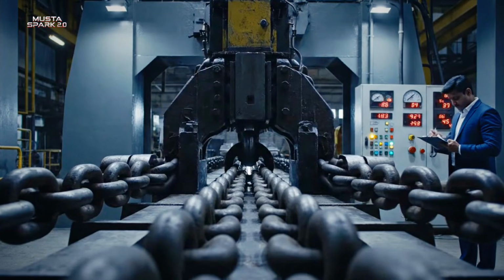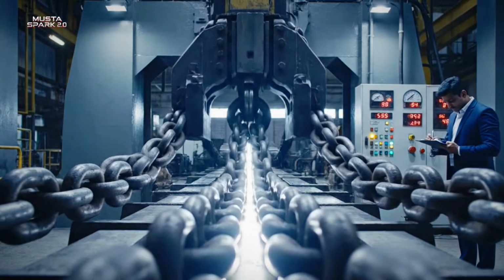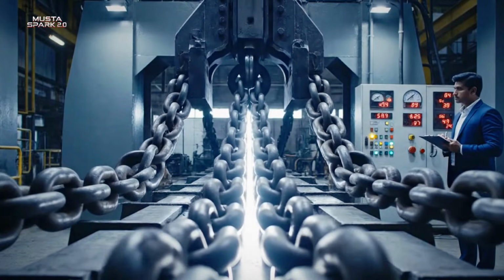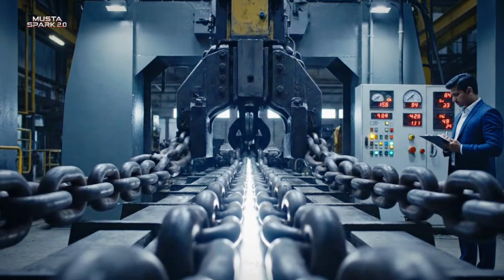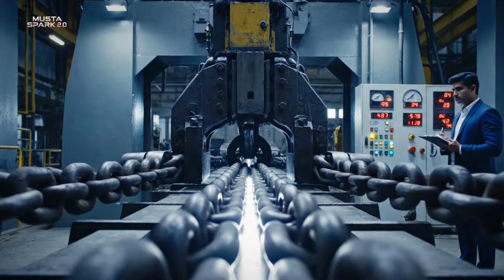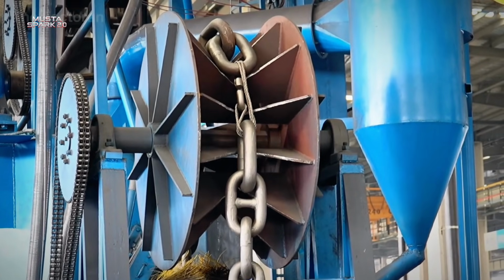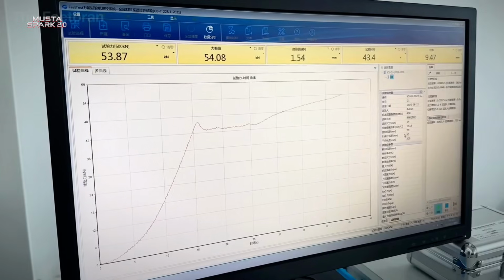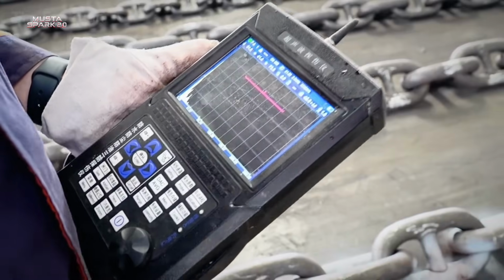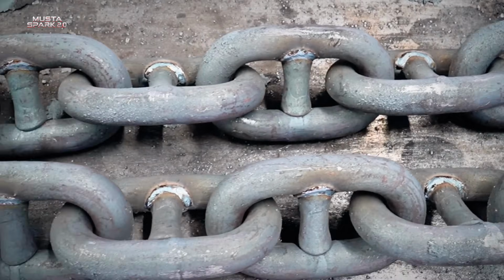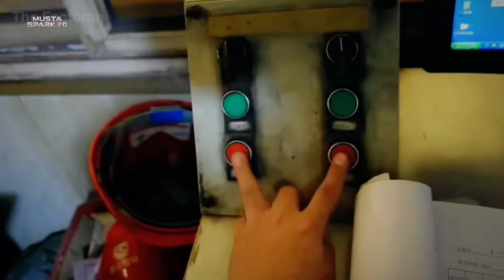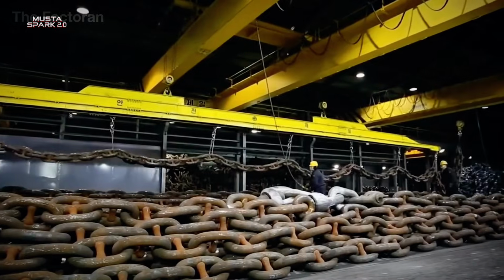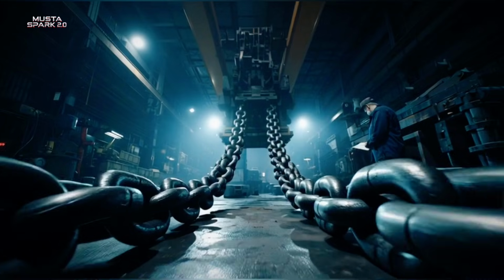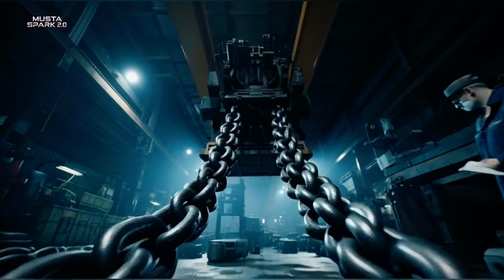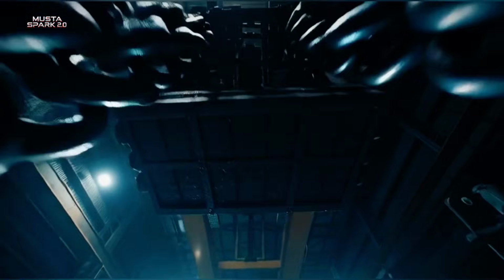The primary test is the proof load test. Every length of chain, every single one, must be subjected to a load equal to approximately 70 to 80% of its minimum breaking load, held for a minimum time period as specified by the relevant classification society. Under this load, the chain must show zero permanent deformation, zero cracking, and zero signs of distress. It either passes completely or it fails completely. There is no partial credit in anchor chain testing. The test is conducted on machines that look like industrial torture devices, which, in a sense, is exactly what they are.